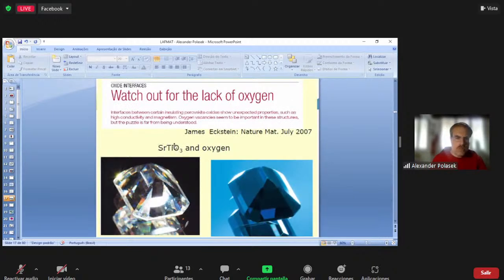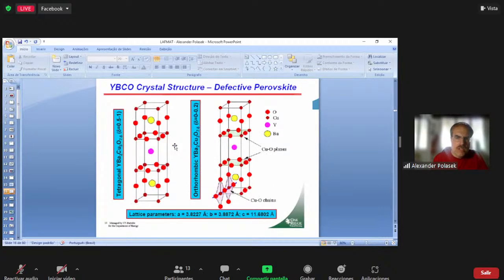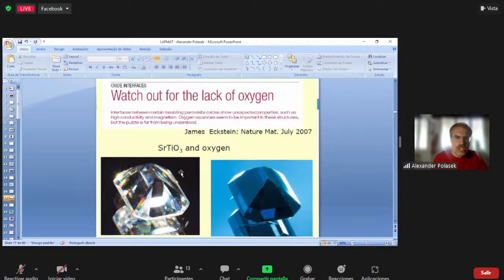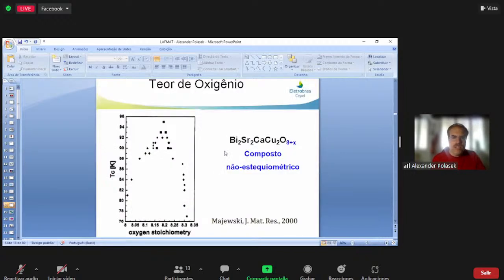For example, this is just an example of perovskite-based materials, not a superconductor. You can see what happens if you change the oxygen content. You can see the same material, the color and the aspect can change totally because of the oxygen content. And here, for example, with a typical bismuth 2212 compound, you can see that a slight difference in oxygen content plays a big role in the TC value. And so it depends on optimal processing conditions to achieve the highest TC possible.